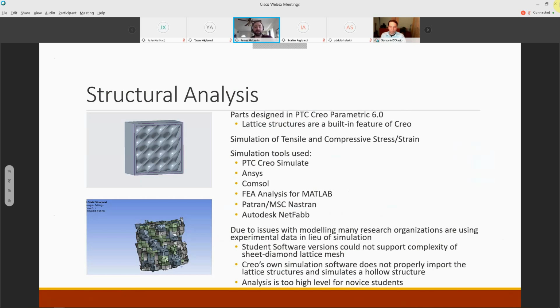We actually found out that many research organizations are just doing experimental data because simulation is so complex. With our program, we were able to do up to about 10,000 facets, and this structure had over 600,000 facets. So it was just a little too high for us, and we had too many struggles with importing.